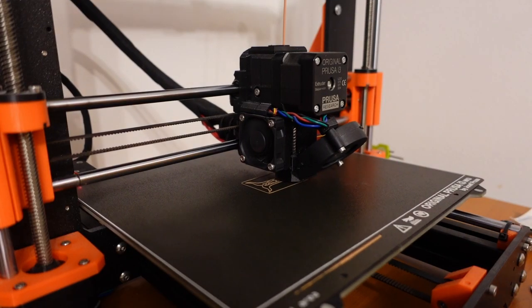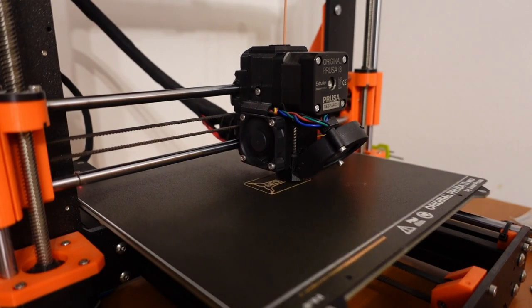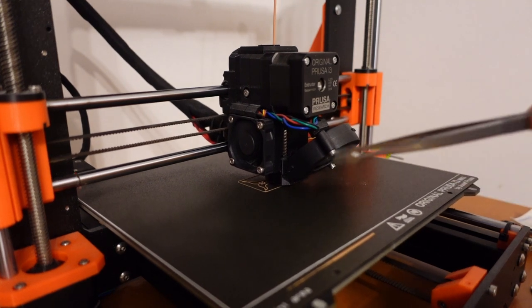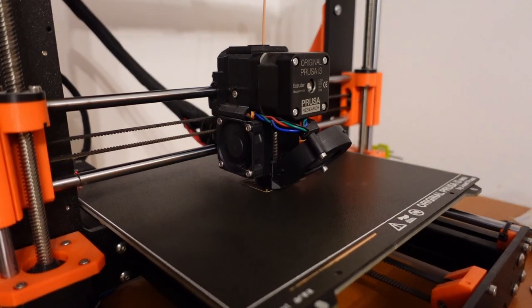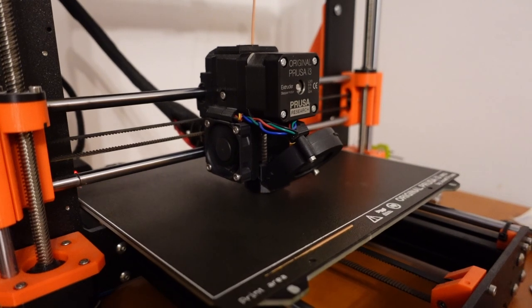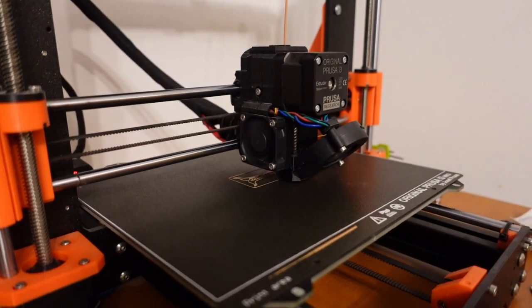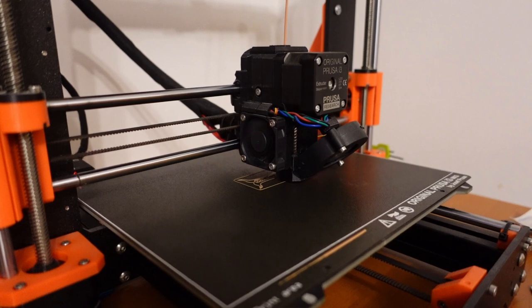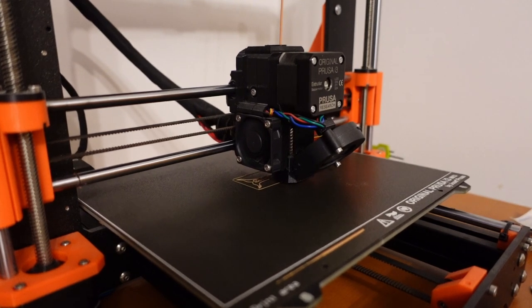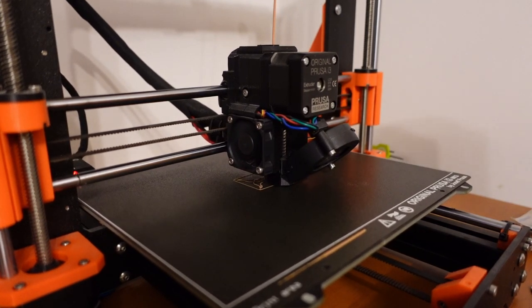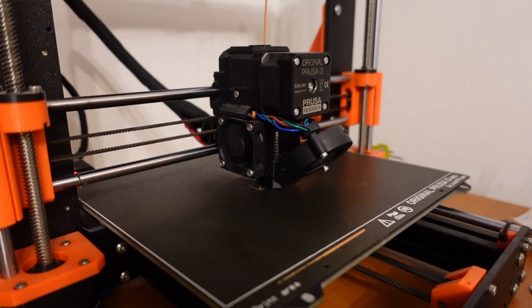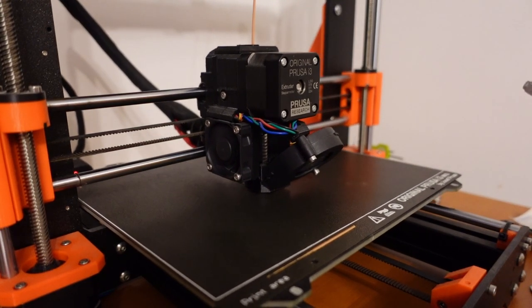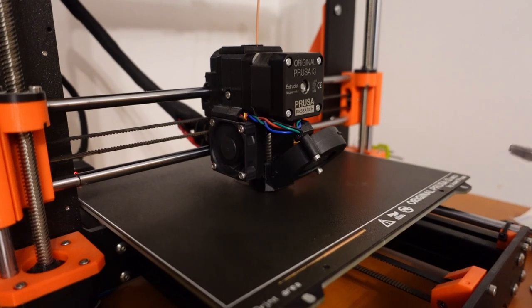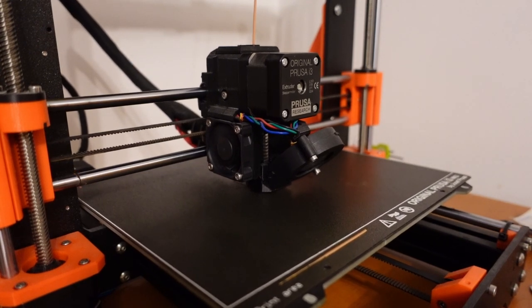I'm starting with the temperature tower at 260 degrees Celsius, and as you can see I'm using a textured PEI sheet. Be careful if you are using a smooth PEI sheet because the PETG might stick too well to it. So in that case you should use some kind of separation agent like glue stick or similar. And I'm not using a dry box or any filament dryer.